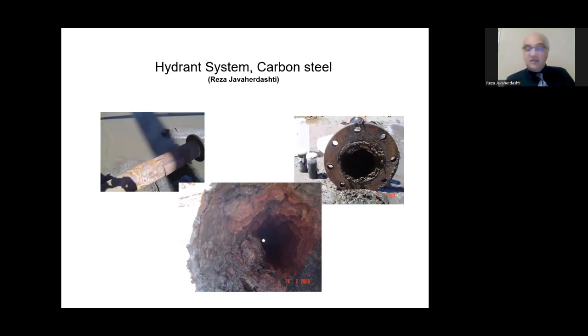I did an RBA based on my RBI, and I mentioned that their fire water rings were quite susceptible to microbial corrosion. They didn't listen. And after 1 month, there was a fire in the plant. When they wanted to control the fire using water, because there were a lot of scales and corrosion products inside the pipe, as you see from the picture below, the pump could not take enough water, and therefore half of the plant burned down. Something that could have been solved for something like $50K, they had to pay $1 million to remediate back in 2006.